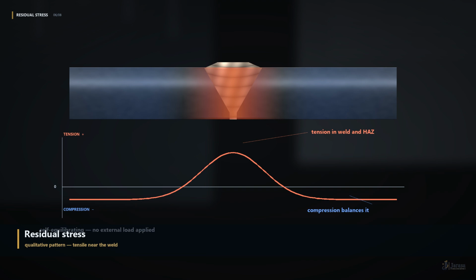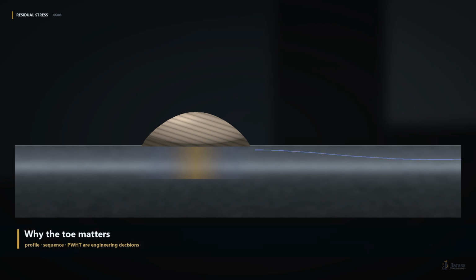Now look at the toe, where the weld face meets the plate. Service stress flowing through the joint crowds into that change of section. Add pressure, thermal restraint and cyclic operation on top of the residual tension, and this is precisely where fatigue cracks begin. That is why joint profile, welding sequence, and post-weld heat treatment are engineering decisions, not cosmetic ones.